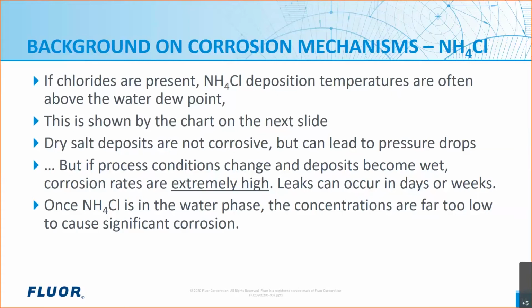There are definitely case histories of leaks that have occurred in days and some in weeks. So they can't be managed, and a lot of times it's very difficult to even know the corrosion has initiated until you have a leak. So that's the main corrosion risk with ammonium chlorides: whenever you can have a risk of forming wet deposits. Actually, once the ammonium chloride is in the water phase, the concentrations are always far too low for that water phase to cause significant corrosion from ammonium chloride.